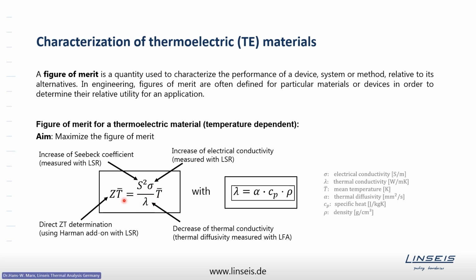The figure of merit may be measured either by measuring Seebeck coefficient, electrical and thermal conductivity, and doing the calculation according to this formula, or there is a method, the so-called Harman method, which allows to determine directly the figure of merit. We'll see later on a later slide how this can be done.